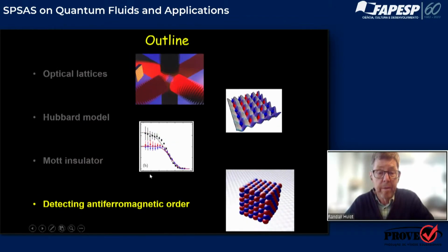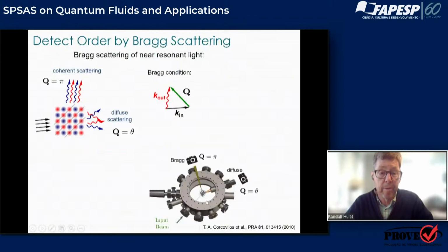So that's the Mott insulating state. That's the precursor to the antiferromagnetic order. But to see antiferromagnetic order, you have to go to even lower temperatures, as I mentioned, to temperatures near the superexchange energy scale, if you want to see something with very long-range correlation. So the way we can measure the correlations is to use Bragg scattering of light.